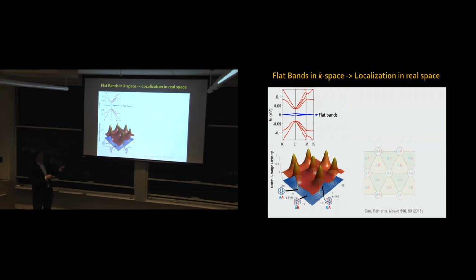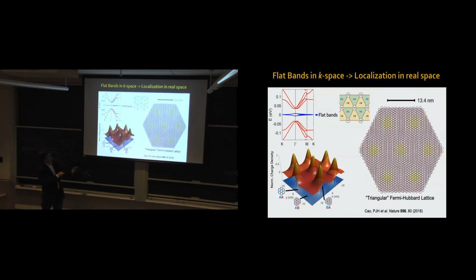So from the top, you can look at it, and it looks like this, schematically. You have this moiré pattern - this is a moiré unit cell, and you have these AA stacking regions where the charge density likes to be, separated by AB and BA stacking regions. If I do a bit more schematic with the lattice, this is what it looks like. These AA stacking regions are separated by 13.4 nanometers at this magic angle.